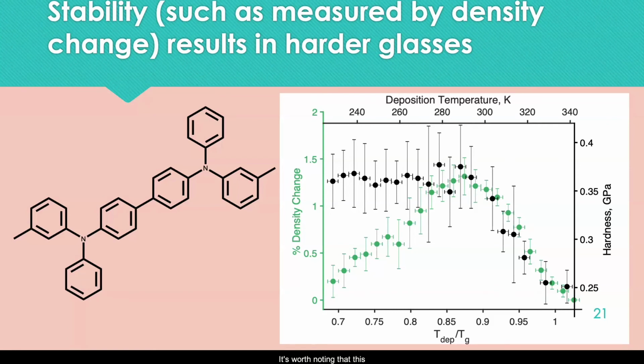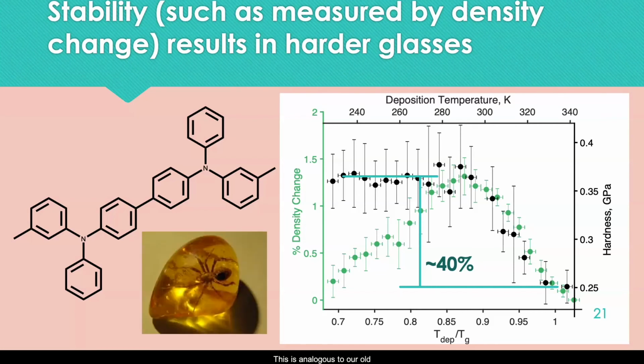It's worth noting that this hardness increase is on the order of 40%, which is significant. Since the density change is only 1.5%, we're seeing really dramatic changes in the hardness based only on differences in temperature of deposition. This is analogous to our old friend aged amber, which is made of a really soft organic material, so soft that bugs can crawl into it and become stuck before the amber ages and becomes harder and tougher. So again, 20 million year old amber only shows a 2% density increase, but really dramatic changes in its mechanics. So again, we're seeing that PVD glasses behave like highly aged glasses.